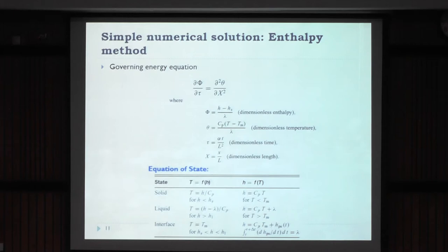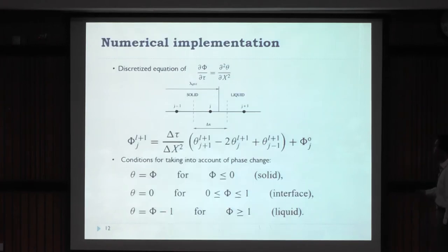Tm is the melting temperature, plus the amount it melts. It is melted, basically, in the sense of the liquid fraction times the latent heat of fusion. This is the way we used to express it. Now, you can have a direct combination like this. The relation between the non-dimensionalized temperature parameter and the non-dimensionalized enthalpy parameter, you can correlate in this fashion, and using the finite volume method, you can discretize the equation in this form.